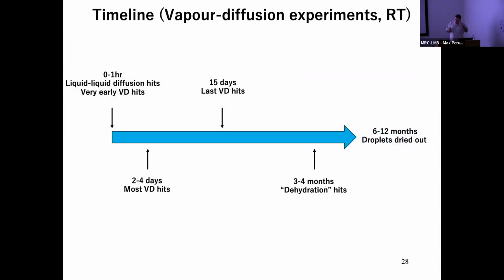So I made this slide because people often ask about assessing the experiment, because this is also a bit of a tedious task, especially if you want to cover a lot of conditions and you do a lot of optimization. So basically, and we're talking obviously still vapor diffusion and at room temperature, there's no strict data available about this, and as for everything, it depends on the samples. But in general, what I see is that when you start your vapor diffusion experiment, which is mixing the protein sample and the condition,